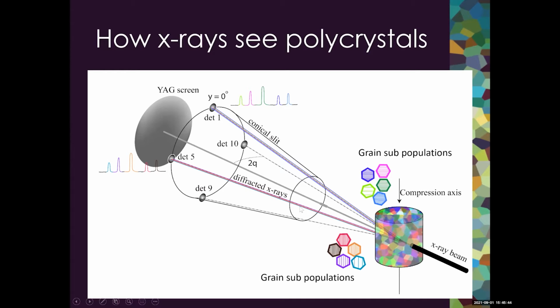And so for energy dispersive X-ray diffraction, we have our X-ray beam coming in, it diffracts inside the sample. So in this group of subgrain populations at the top here, which sends the signal to detector 1, we're looking at grains that have lattice planes with varying D spacings that are roughly normal to the compression direction. And so when we look at the X-ray diffraction pattern, we see many peaks where each peak correlates to a specific group of grains that have the lattice planes perpendicular to compression.